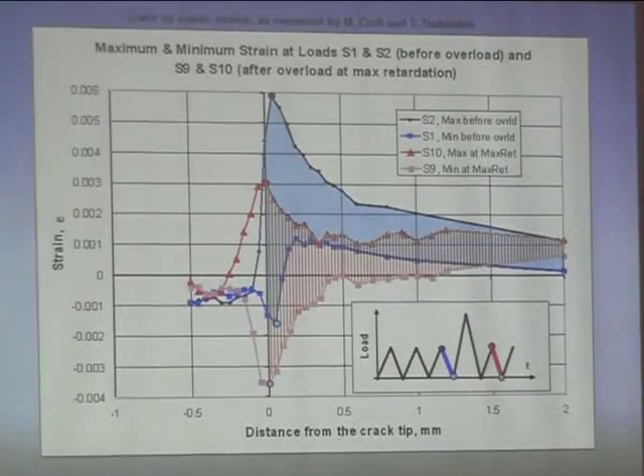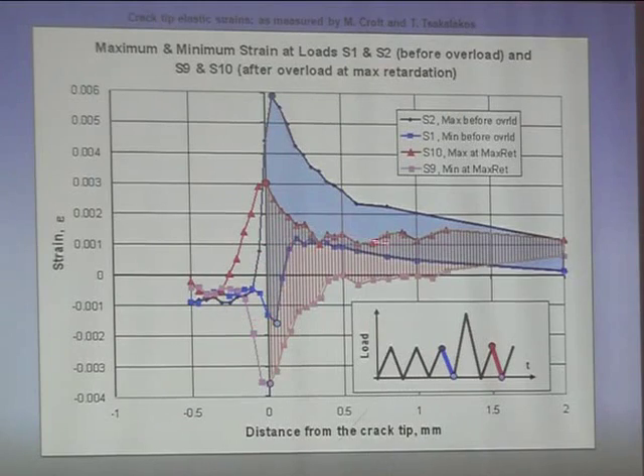So after that, Mark Croft and Professor Tsakalakos from Rutgers University measured those strains. So actually it was done simultaneously. And this is what you see for the same experiment, the same specimen, the same material, the same crack length. These are the maximum and minimum elastic strains before overload, and those are after overload.